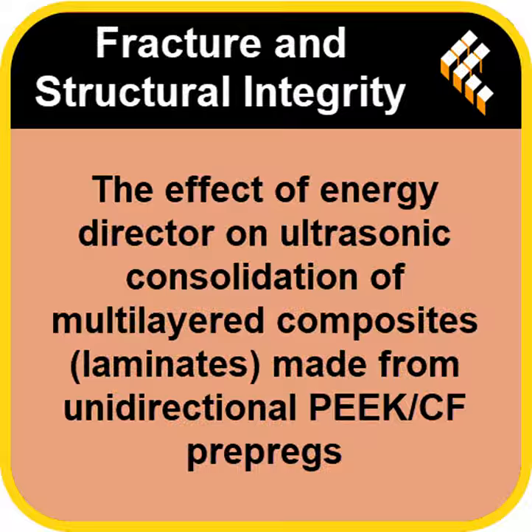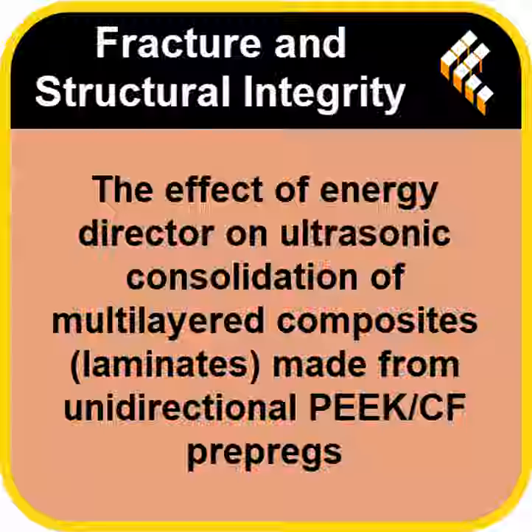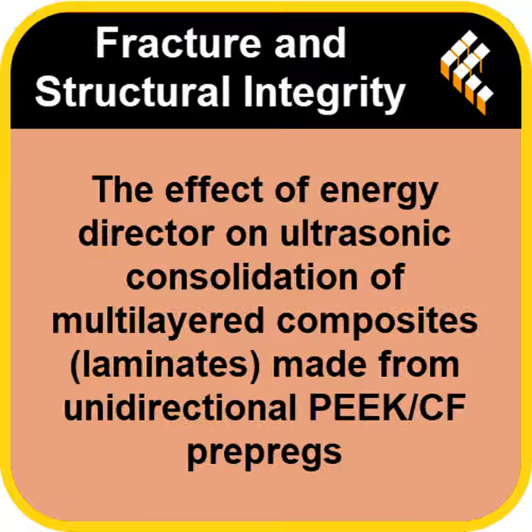It meant the bond was so strong the crack had to really fight its way through the structure instead of just zipping along a weak layer. So this raises a really important, almost non-technical question. You have a high strength point: 60 MPa at 1200 milliseconds, no ED.